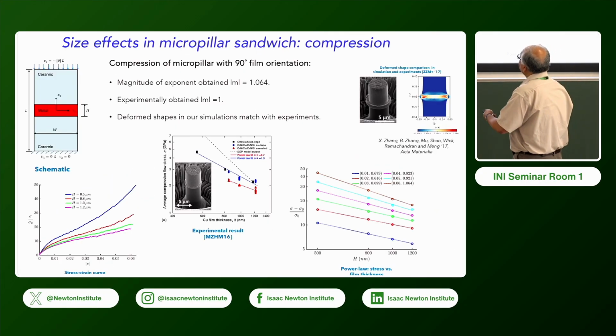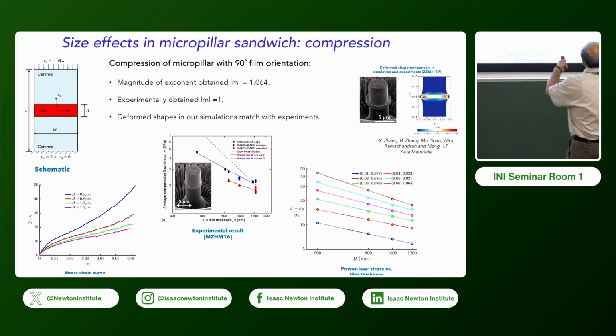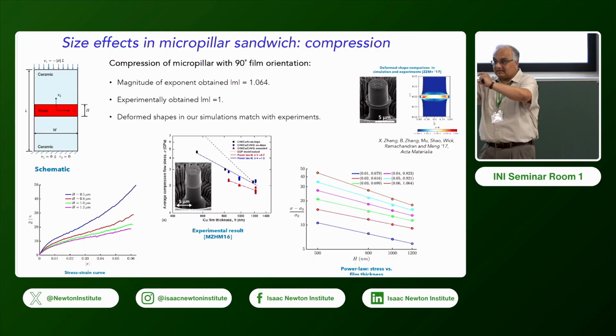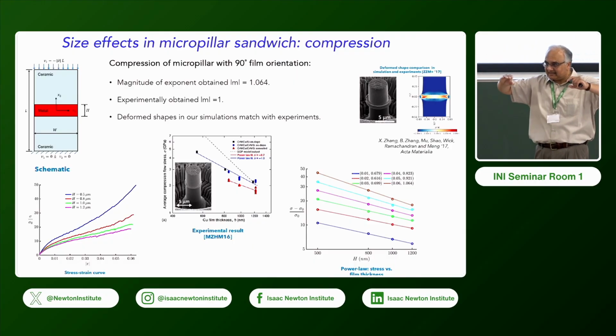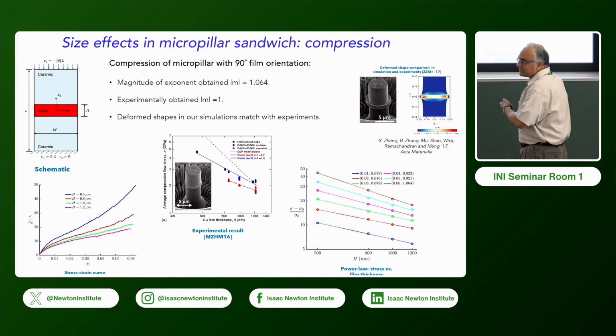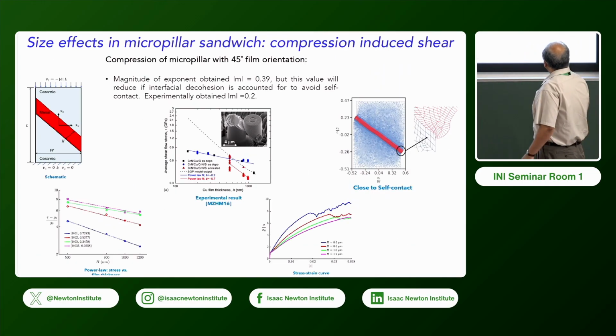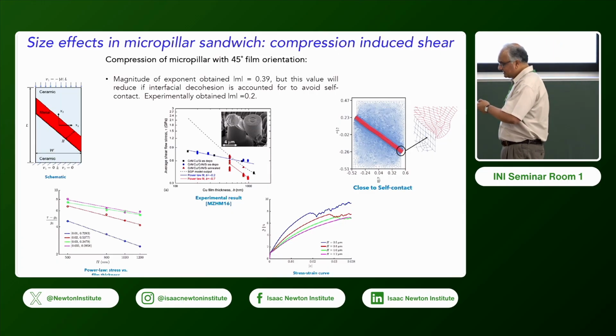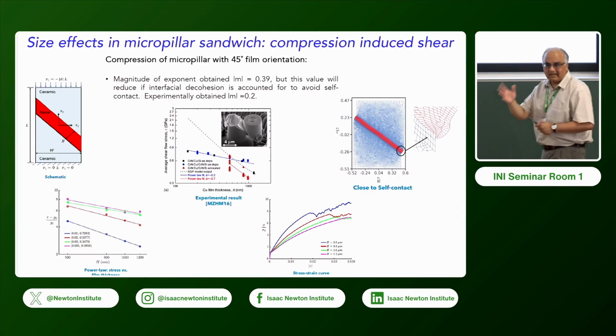And so we did it for the actual case. This is in Acta, the paper. We get that, and this is an experimental plot of the film. The film actually expands out. There's fracture along the interface. We didn't allow for fracture, so that's that. And in this 45-degree orientation, there's not a size effect, etc. And I think that's a good place to stop. Thank you very much.